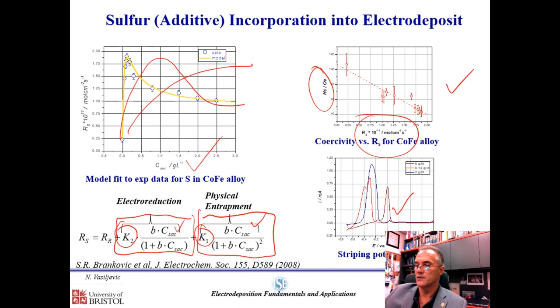And then, if you use 2 grams, which is much lower incorporation rate, the peak is shifted to more positive potential. So there's an optimum between the benefit and drawback when we think about the overall properties of the deposit, and you need to understand really well what additive does, how it does, in order to design the best process to have the best properties of your material.